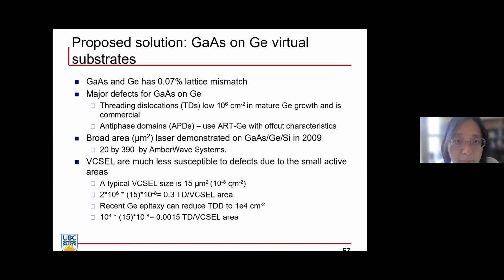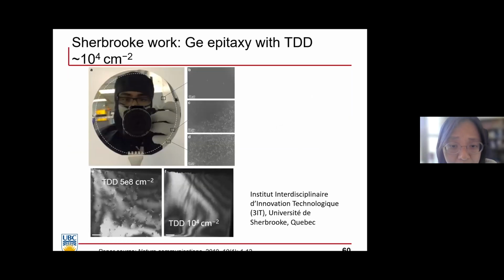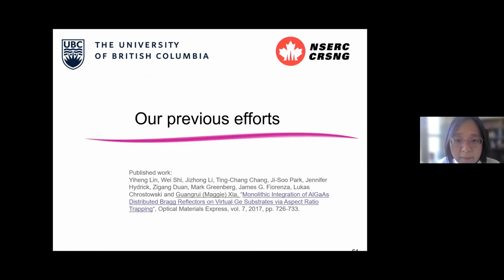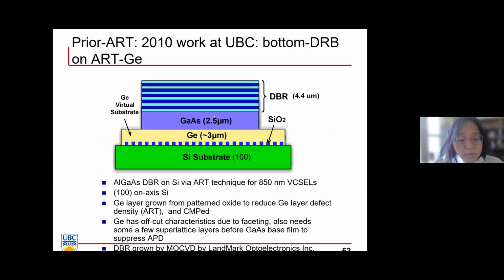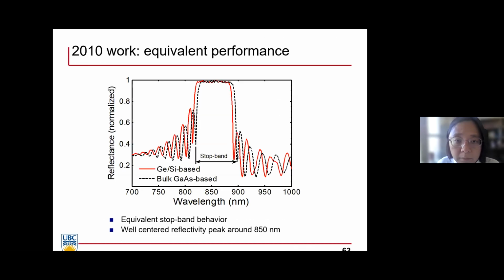I'll skip some of the more technical details, but let me show you what we have. Also, one thing is that germanium epitaxy nowadays can be much better in quality with much less dislocation density here. So in our previous efforts, we built gallium arsenide based distributed Bragg reflector DBRs on virtual germanium on silicon 100 substrate. If you see the stop band characteristic, which is reflectance versus wavelength, you see how this germanium silicon based DBR really is almost on par with the bulk gallium arsenide based DBR. So that's very promising